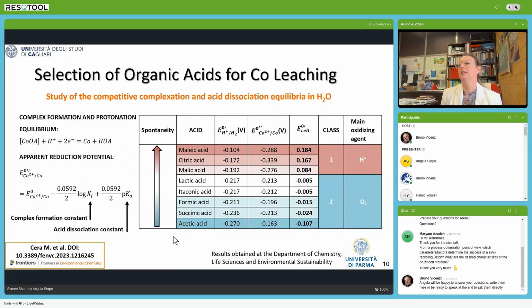For this reason, we made a study in water solution to highlight the possibility for different acids to play the role of oxidant in the solution or not. And we divided these into two classes, calling them class 1 and class 2 acids, where acids with a lower pKa and higher capability to coordinate the metal may play the role of oxidizing agents in solution.